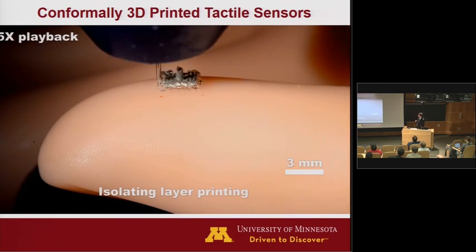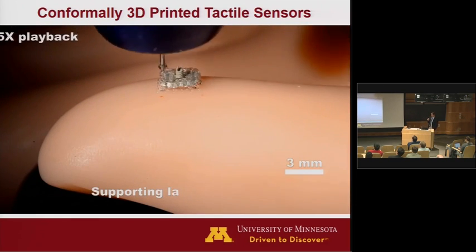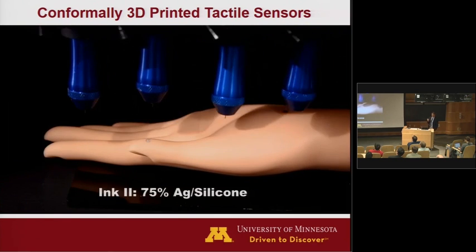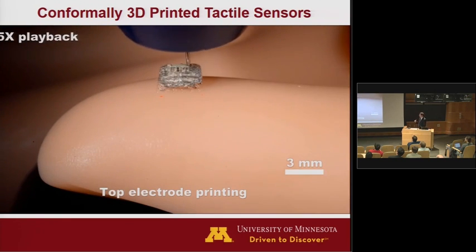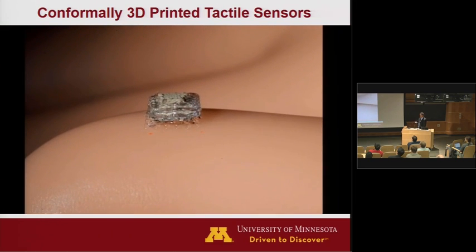And this is the sacrificial supporting layer. So one thing you're not seeing here is the fact that this finger that you see is actually a curved surface. And what we did beforehand is we 3D scanned that curved surface, and this device is actually being conformally printed. It's hard to see here, but it's actually adapting to the curvature of that finger as it's conformally printed onto the surface. And in fact, if you want to print on your real hand, you have to take into account the fact that your hand is going to vibrate a little bit. So now one of my students, a talented student, has developed an algorithm that can track motion of a hand in real time in order to do this. And he's even shown me amazing videos where he's taken paper and crumpled it, and then uncrumpled it, and then he can track the topology of the paper by doing a scan and print type of approach.